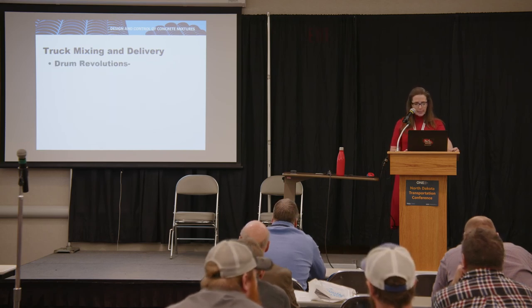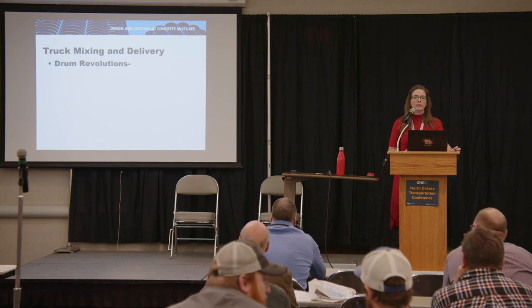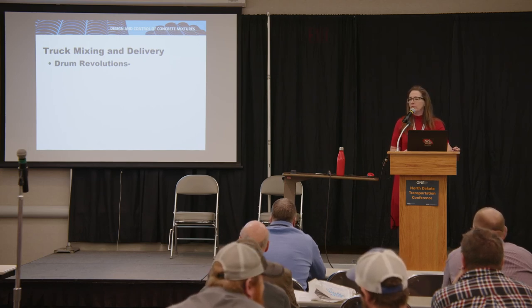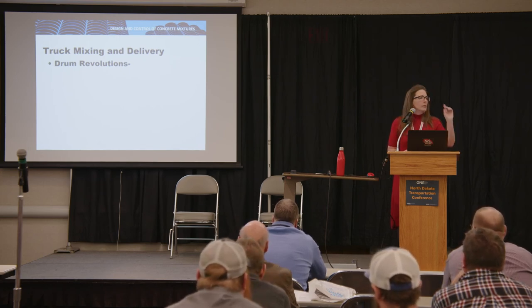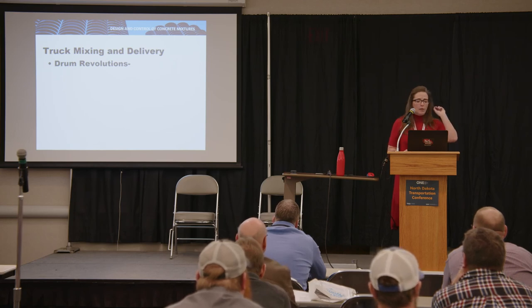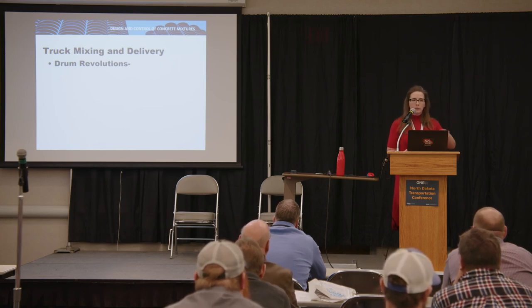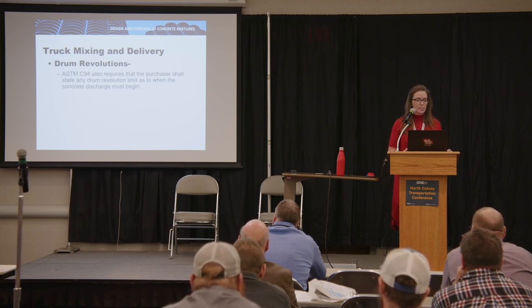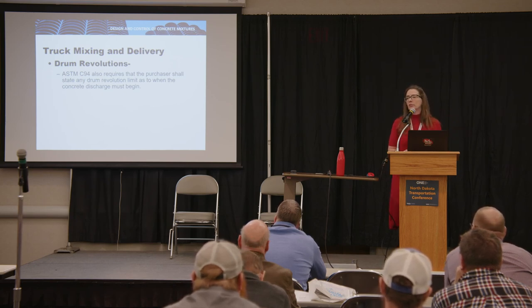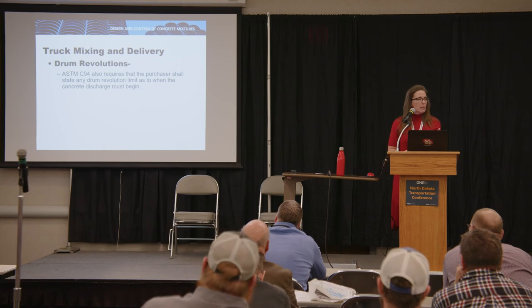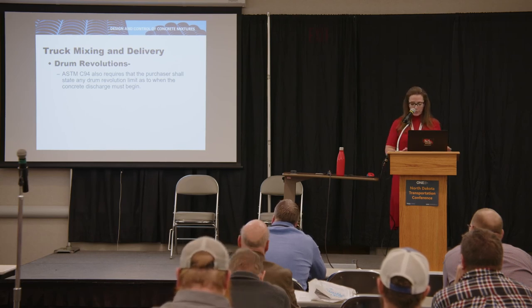This one concerns me less. This one's been around forever, too. What's our default drum revolution? 70. That's mixing time, but that was a very good answer. 70 is your default mixing revolutions, and our default for a maximum number of revolutions was 300. So 70 is still there. We still need thorough mixing. And then you can be at agitation, or if you're the driver that doesn't like your drum to turn, you just drive it without turning it until you get to the site. But once you hit a maximum number of revolutions, that truck is supposed to be rejected.